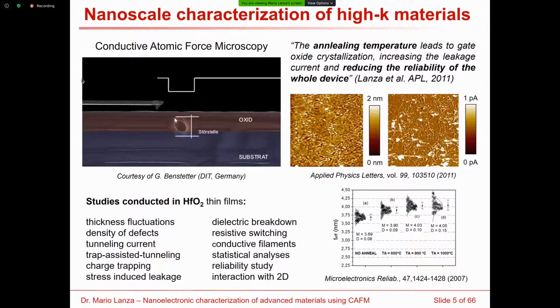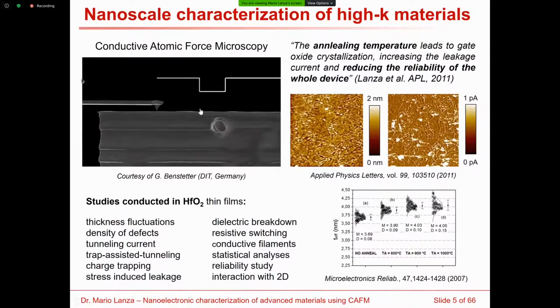And then if you can scan the surface of the sample and move the tip from one line to another, you can make a three-dimensional map of the electrical conductivity of the sample that you're going to study. And at the same time, because it is based on atomic force microscopy, you can also construct one topographic map. And these two images are constructed simultaneously, but at the same time independently.